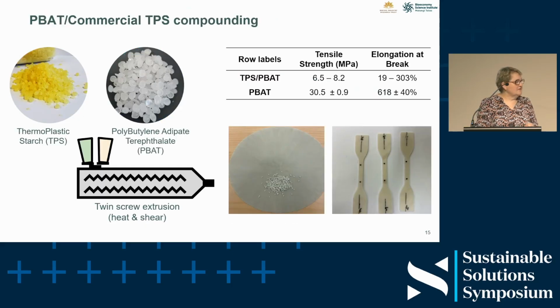Then to add to the plasticity, they added a copolymer, which is, and I think this is why I didn't become a chemist because I can't do these words, polybutylene adipate terephthalate. I'm going to call it PBAT, much easier to say. It's basically a fully biodegradable and very flexible polymer. So if you mix it in with your thermoplastic starch, it increases the tensile strength and the elongation numbers.